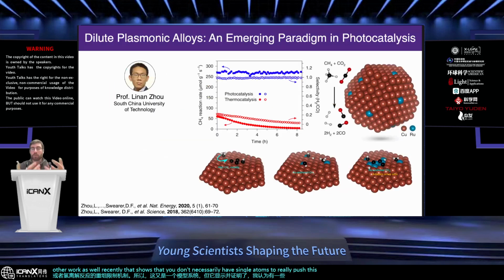And that's why the field that I'm pursuing in my lab is this area of dilute plasmonic alloys, not necessarily at the single atom limit, but in the regime where we can control active sites and surface chemistry, but not completely damp out that plasmon resonance that's so important.